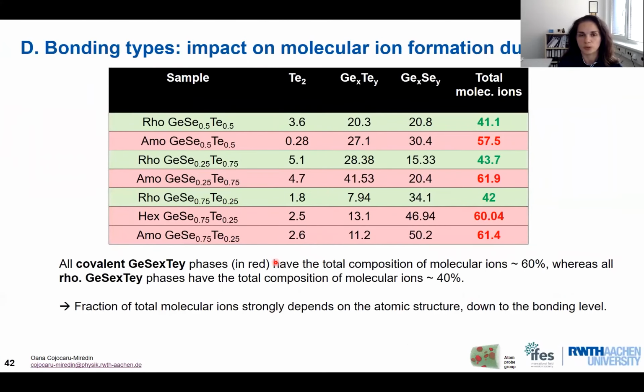Another example is shown also on this slide, where I show compounds which have exactly the same chemical composition but different structure and also different bonding mechanism. We see that for the green one, we have a total of molecular ions of about 40%, but for the second one, although we have exactly the same chemical composition but a different structure, an amorphous compound, and we know that this is also a covalent compound, we have a much higher fraction of molecular ions.